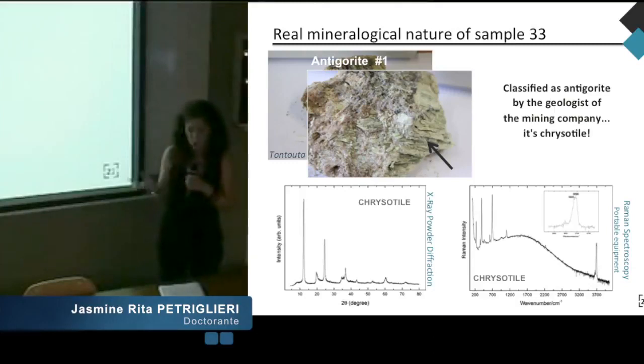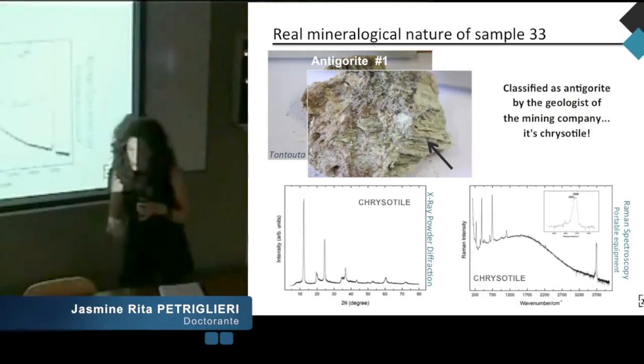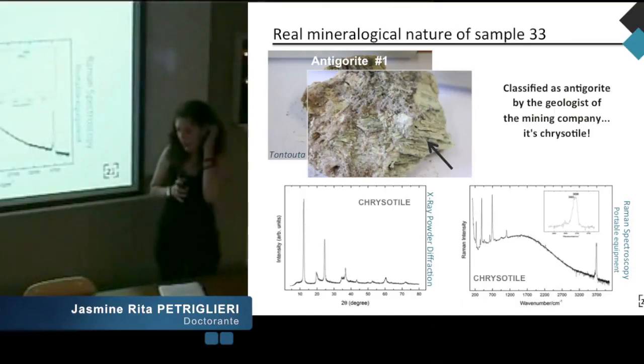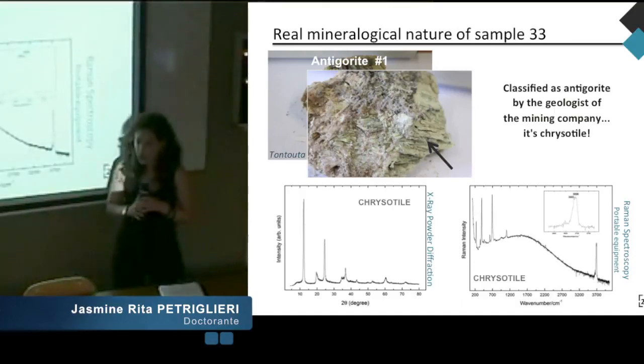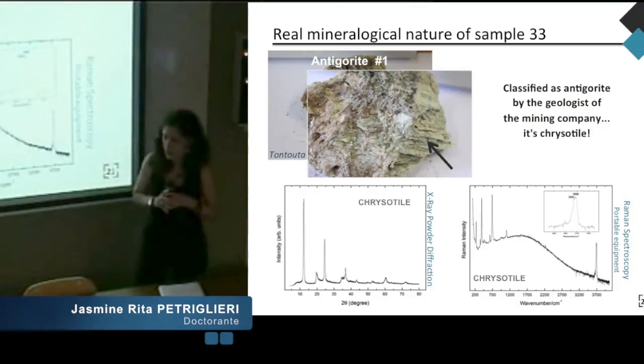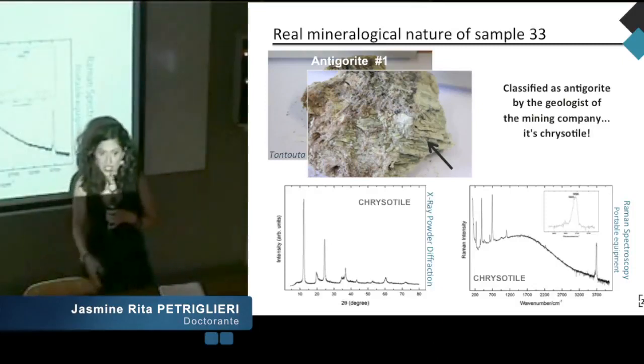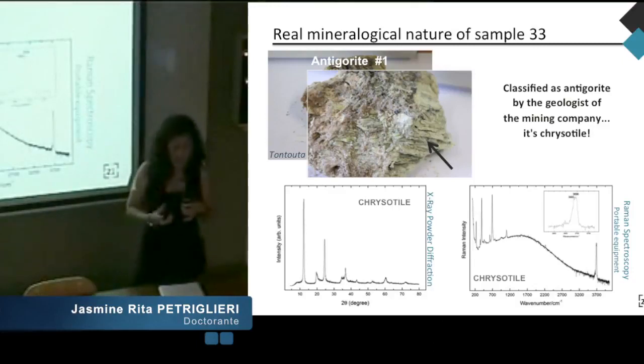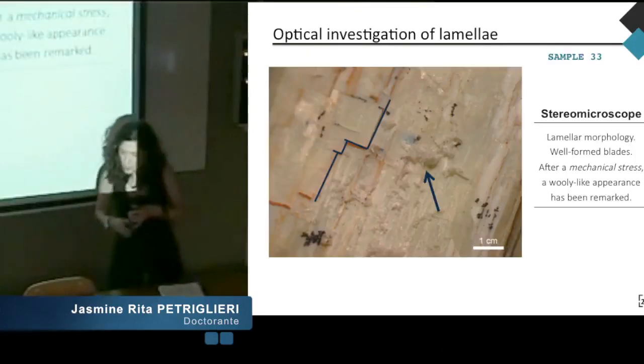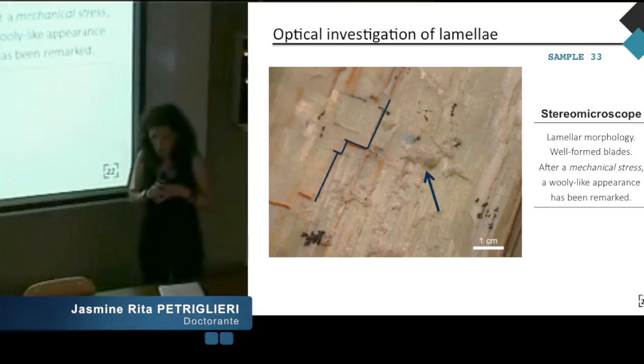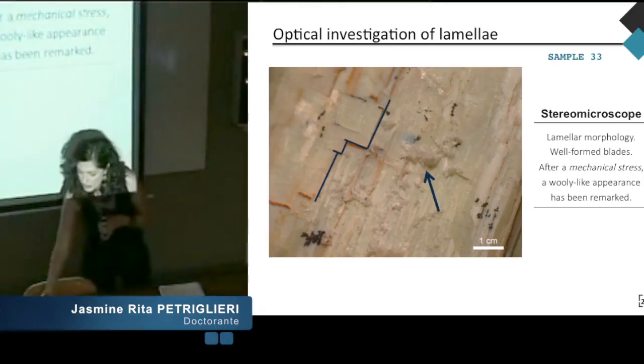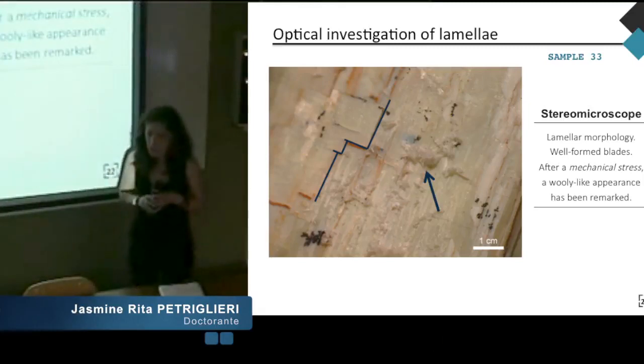a color from green to white. And the first preliminary X-ray powder diffraction and portable Raman investigation states that it is chrysotile. We decided for this reason to characterize these samples in more detail in order to better understand their real mineralogical nature. At the stereo microscope, the sample appears characterized by a lamellar morphology, but just after a mechanical stress on the surface, we observe the appearance of individual fibers.